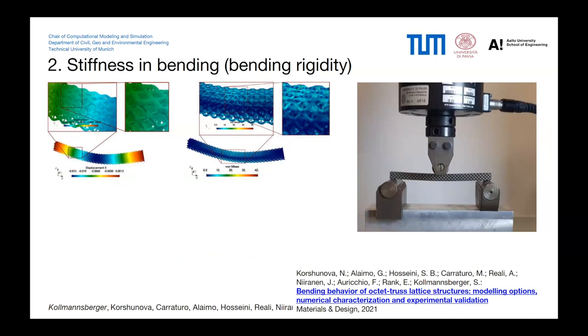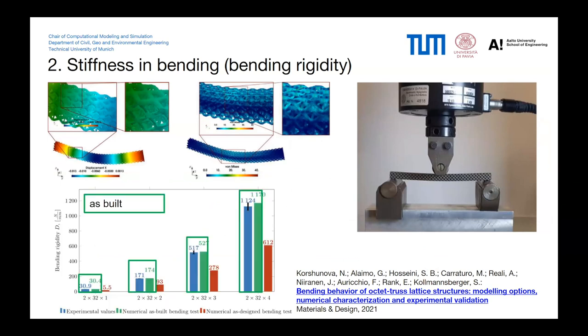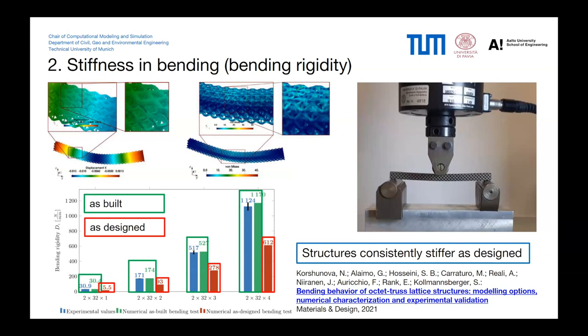However, when you do this on these geometrically exact CAD models, you get about only half the stiffness. The same situation reflects in bending. We've done the bending tests, performed the bending tests as shown to the right. I'd like to show you quickly the comparison of the bending rigidity here of the numerical values of the as-built structures here in green compared to the as-designed structures here in red. Again, we see that we get a consistently higher stiffness, about twice as high in the as-printed structures or as-built structures as in the as-designed structures.